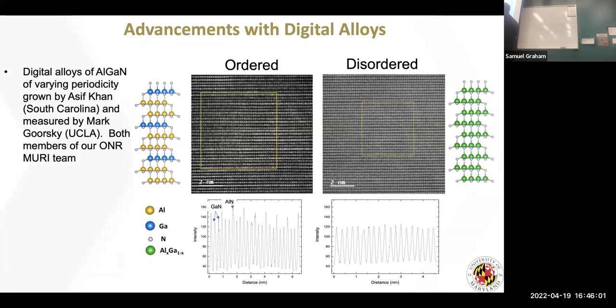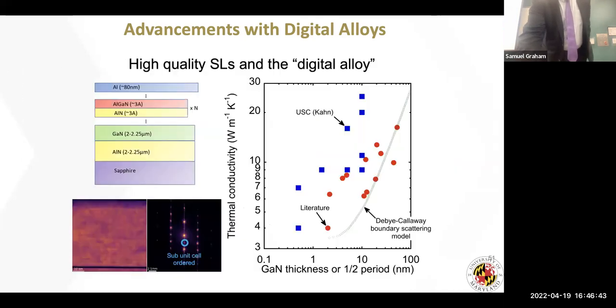And so here's what a digital alloy looks like, which I think is pretty amazing. You can see these layers, you can see the atoms here. When they do the analysis of the TEM, this is grown intentionally: 2 layers of GaN, 1 layer of aluminum nitride, 2 layers of GaN, 1 layer of aluminum nitride. So they can actually put these things down with very high precision. As you start growing some of these materials, you have very ordered crystal structures versus this unordered one here. This is aluminum gallium nitride, and this is an aluminum gallium nitride digital alloy. What we believe is that you will see different modes in this material than you will in this one. These are things that we're looking at, especially as you start bringing materials together.